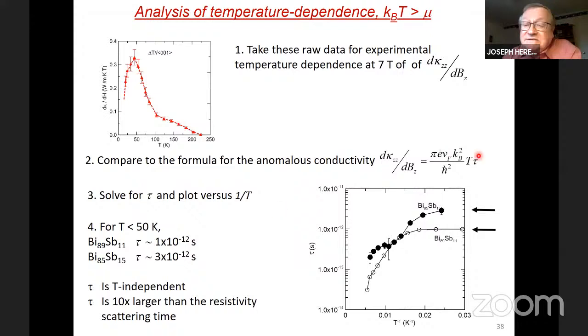Well, so we compare the data and the model, and out comes only one parameter, tau, which we plot here as a function of 1 over T. And so you see the tau values are here for the 15% sample and here for the 11% sample. And then we make two analyses of this. First, we look at the low temperature limit, so high 1 over T. And here's 10 to the minus 12 seconds, and 3 times 10 to the minus 12 seconds. These numbers we can then compare to the scattering time we get out of the mobility at zero field. And they are 10 times larger than the scattering time at low temperature. So that is one observation.